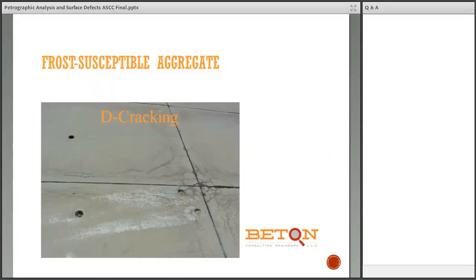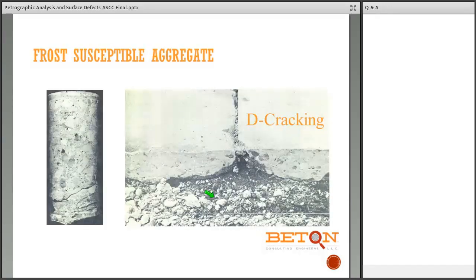D-cracking basically is either referred to as durability cracking or simply D-cracking, and basically it's characterized by a characteristic crack pattern that wraps around the joints. Usually the method of sampling is to take a sample away from the joint and a sample at the joint, and basically you'll see something like this, perhaps away from the joint on the left. There it is. You'll see cracks coming up from the bottom, and then as you get closer to the joint, you'll have cracks up near the surface, so you can see the typical profile of D-cracking, and that's not a very pleasant thing for many contractors or MnDOT or DOT personnel.